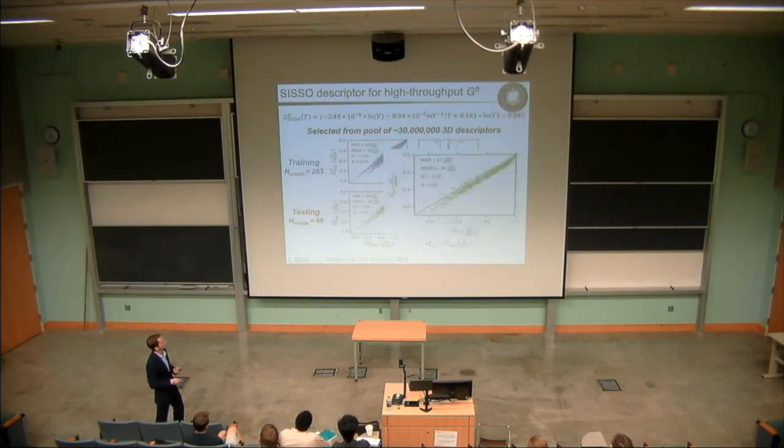And so to give a general idea of how accurate that is, we also look to these explicit DFT-based calculations of the phonon free energy using the quasi-harmonic approximation. So this is using that computationally expensive technique I mentioned earlier. And what we find is that their error bar is about 40 meV per atom. So somewhat remarkably, using just this simple model that includes 3 fit coefficients, we're able to get close to this really computationally expensive approach.